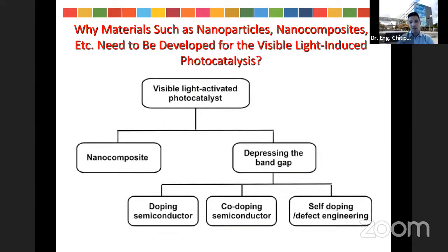As I mentioned in the previous slide, due to the big energy band gap of the semiconductor, it can work only under UV light, because it needs enough energy to excite the electron from the valence band to the conduction band. However, normal solar light contains only 3 or 4% UV light. The major part of solar light is visible and infrared light. So numerous efforts have been made to produce nanomaterials, such as nanoparticles and composites.